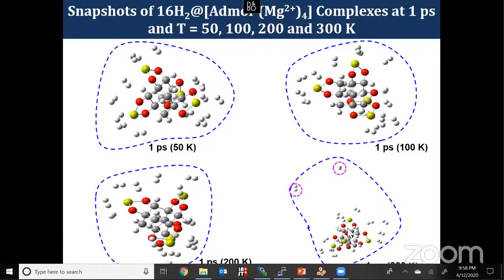The one important thing is the structure of the backbone of the moiety is not deformed or ruptured near room temperature. That means it's forming a stable substrate. So this means that we can use this material to trap hydrogen molecules near room temperature.